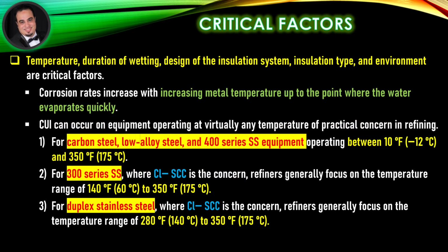Critical factors: temperature, duration of wetting, design of the insulation system, insulation type, and environment are critical factors. Corrosion rates increase with increasing metal temperature, up to the point where the water evaporates quickly. CUI can occur on equipment operating at virtually any temperature of practical concern in refining.